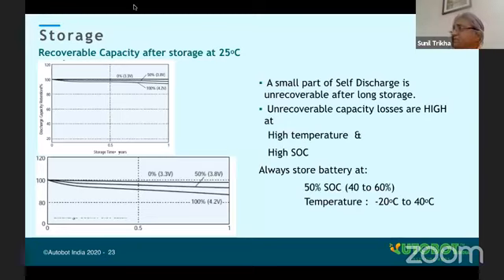So the most important thing here is that the unrecoverable loss depends upon two things. One is the temperature. If temperature is high, the unrecoverable loss is high. Secondly, what is the state of charge? If a battery was fully charged, 100% charged, and you store it for a long time, the unrecoverable loss will be high. But if you discharge the battery to 50% and store it for a long period, this loss will be negligible. So this is an important factor one must keep in mind. Whenever we are storing a battery or transporting a battery, we always discharge to 50% and then transport.